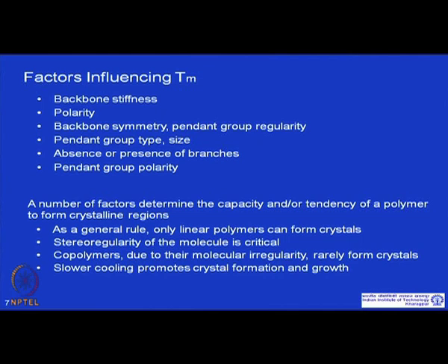Copolymers, we are talking about random copolymers, due to their molecular irregularity rarely form crystals. And if you cool the polymer melt slowly, then the polymer chains get more time, and they can crystallize easily, or the crystallites can grow to a bigger size.